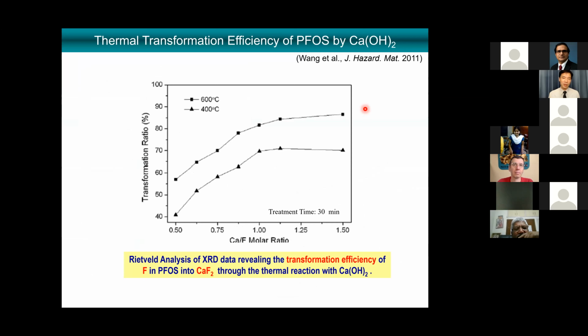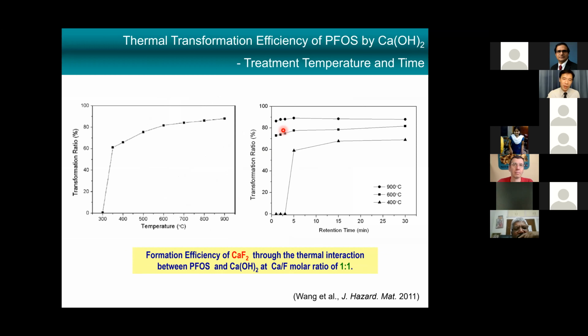And now we have to use X-ray diffraction to tell people how to control them to generate the reaction that we want. Again, we find out you don't have to put too much calcium, you only need to put in just enough. Generally, about 1 part of calcium to 1 part of fluorine, at either 400 or 600, you should probably have a stable capture rate. And as I was saying, if you're using lower temperatures, you probably need about 5 minutes. But if you use relatively high temperature, in less than 2 minutes you can have the reaction achieved. And again, at relatively higher temperatures, the fixing rates are in general proportionally higher when you're using the calcium fluoride mechanism.